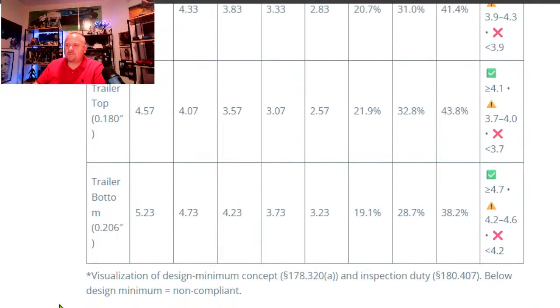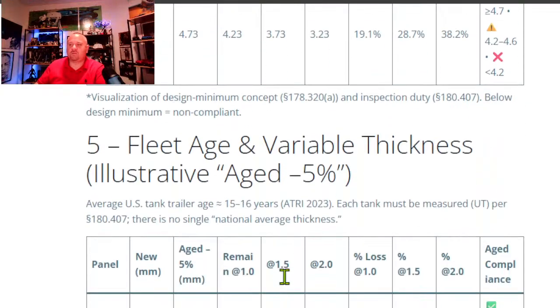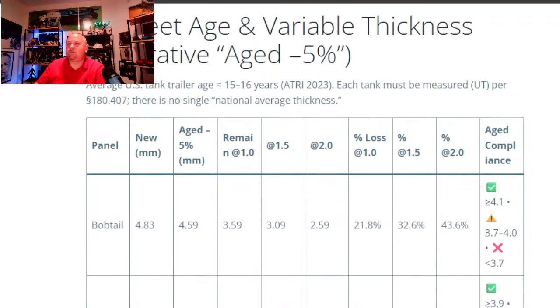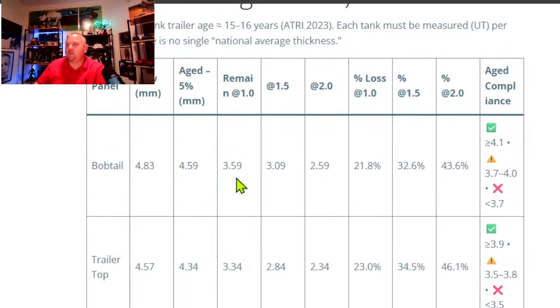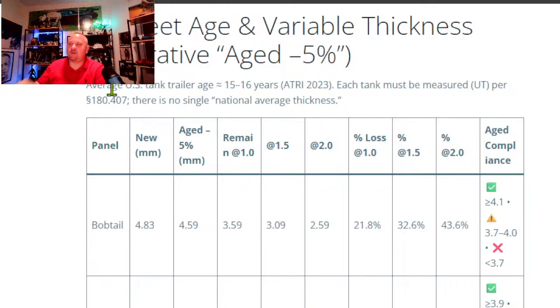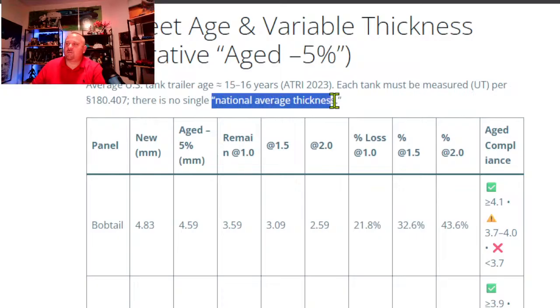It's out of compliance. This is the visual design minimum concept. This is the DOT regulation where these numbers come from: 178.320A, and inspection duty 180.407. Below design minimum equals non-compliant. Now, these are fleet age and variable thickness, illustrative, aged by 5%. These are the numbers in bold down here. This is the average U.S. tank trailer age, 15 to 16 years old, per ATRI 2023. Each tank must be measured by UT per DOT safety regulation 180.407. There is no single national average thickness. These are averages for 15 to 16 year old tankers according to the ATRI 2023.